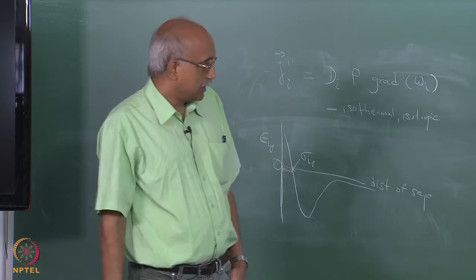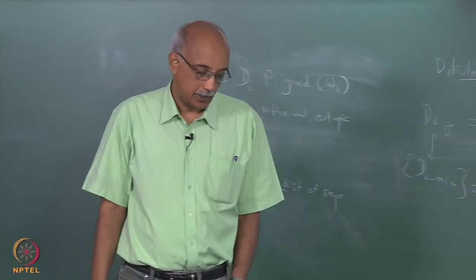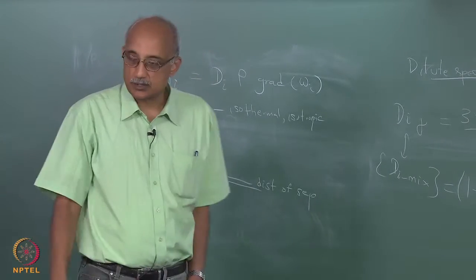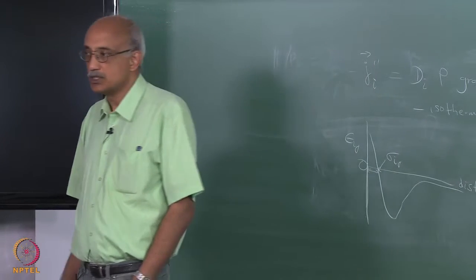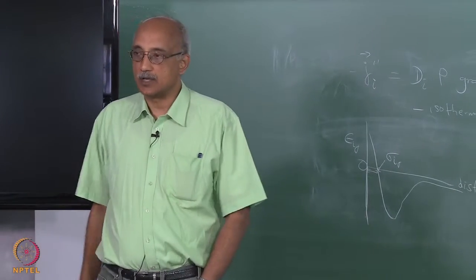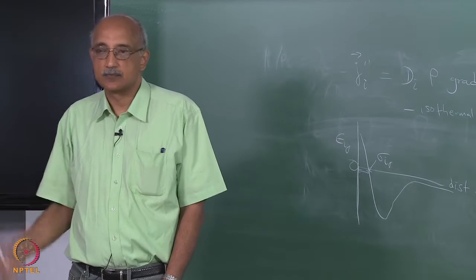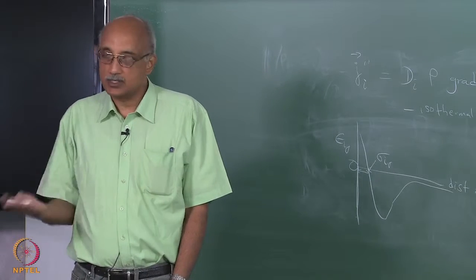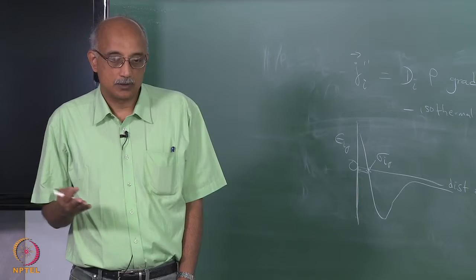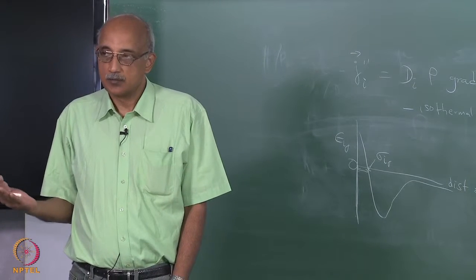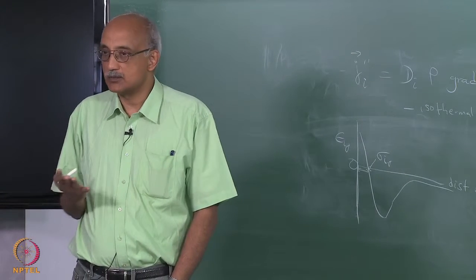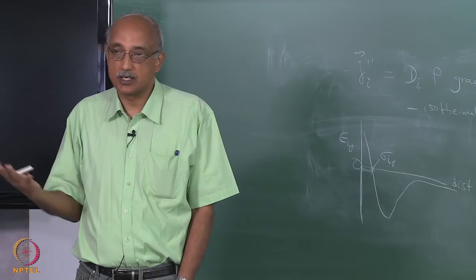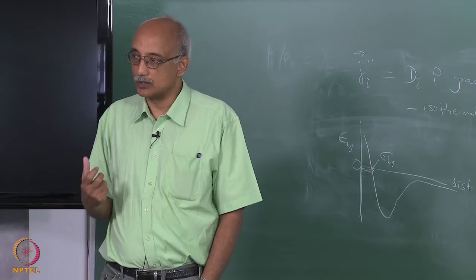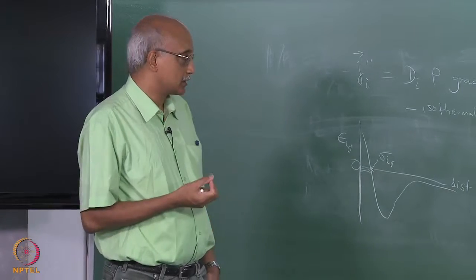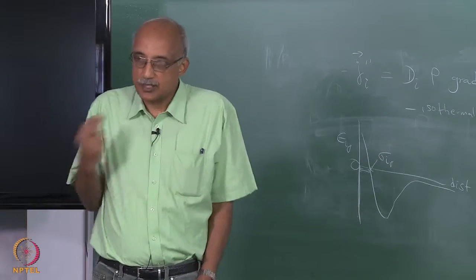Now, in the case where you have a heavy species, let us say that the molecular weight of the diffusing species exceeds the molecular weight of the carrier gas, which can very easily happen in CVD systems because we use H2 as a carrier gas, but the depositing species may be SiH4, which is much heavier and larger than the H2 molecule. In such cases, how do you estimate the diffusion coefficient?